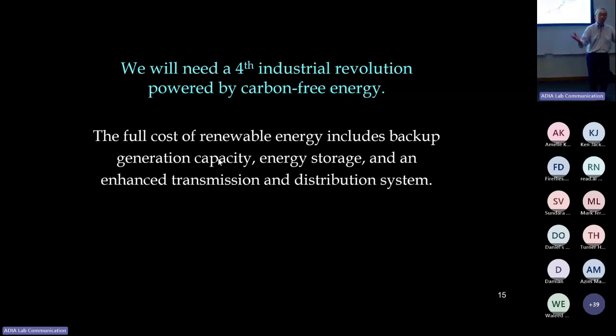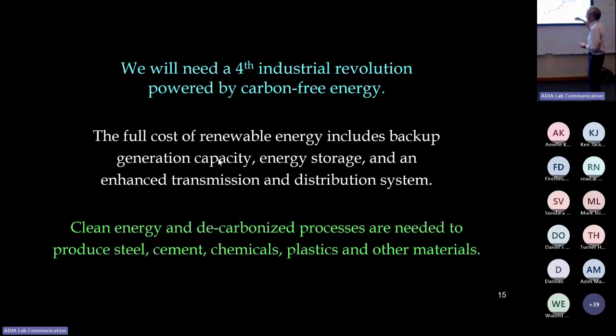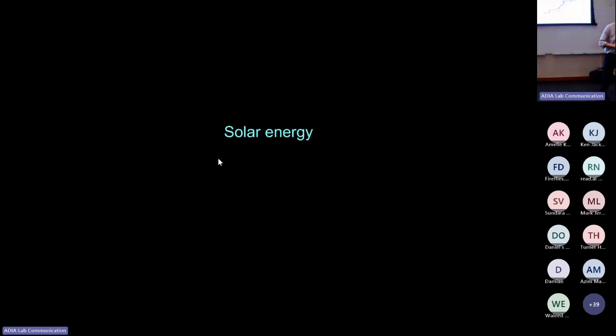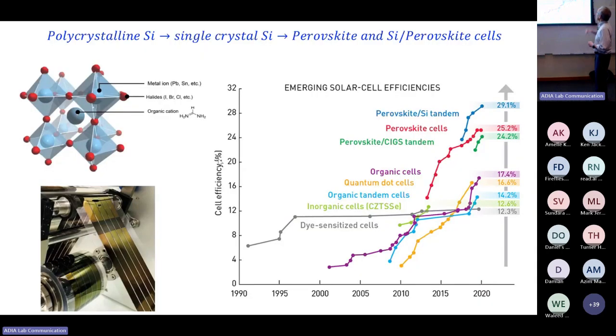All right, solar energy. A new kid is on the block. Whether it becomes commercialized or not remains to be seen. These are called perovskites, very complex materials, but huge progress in perovskites or in perovskites with silicon. And so these are the so-called rates of cell efficiency. In the past, perovskites would only last weeks, months. And now there are two groups that report accelerated lifetime testing of at least 15 years.